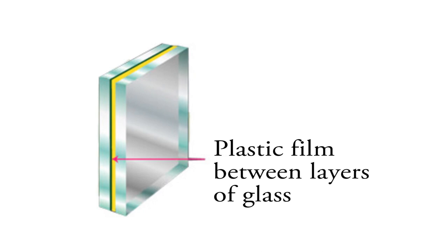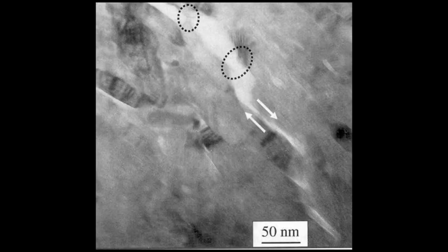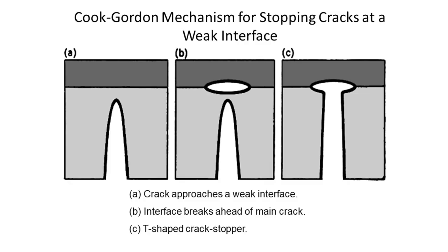A good example of this phenomenon is safety glass in windshields. A thin film of plastic is placed between two panes of glass to act as a weak interface that redirects and blunts the energy of the crack from transferring from one sheet of glass to the other. Perhaps a more appropriate example is tooth enamel. It is very common for tooth enamel to have cracks that have not propagated to the point of structural failure. Each enamel prism is surrounded by a protein sheath, creating relatively weak bonded interfaces that blunt and redirect cracks, making the enamel fracture tough. If there were a strong bond between enamel prisms, tooth enamel would be brittle and our teeth would shatter with relative ease.